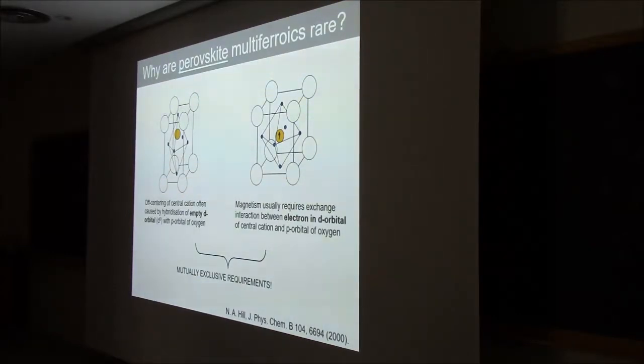These are rare. I'm not even going to discuss why they are rare. Just take it from me. There's very few materials that are truly multiferroic. In fact, the standard one is bismuth ferrite, and bismuth ferrite is not even a ferromagnetic material, it's an antiferromagnetic material, and there's some reasons why that is the case. They are rare, and the jury is still out as to whether we will manage to make such a multiferroic memory. If we have time at the end, and you want, you can ask me as to why we think these materials are rare.